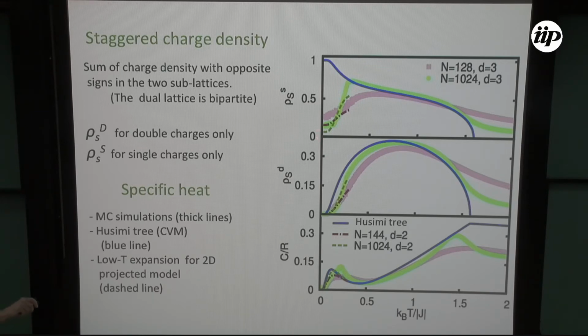So at 0, you have this density 0, but as soon as you put a little temperature into the system, it jumps into a state where this staggered density is non-zero, and it eventually goes to 0 when you have the second transition. So there's this temperature range where the system has single charges and also has some density of double charges. You see here that it jumps to 1. As soon as you put in a small temperature, it jumps to 1.